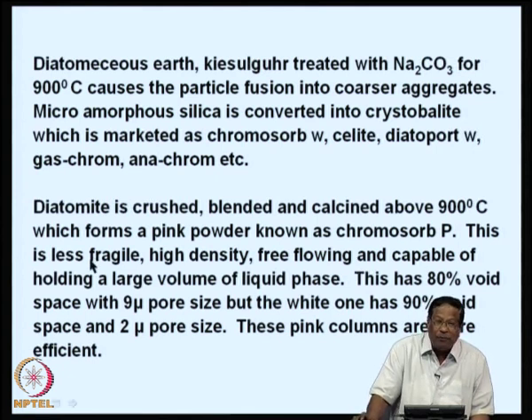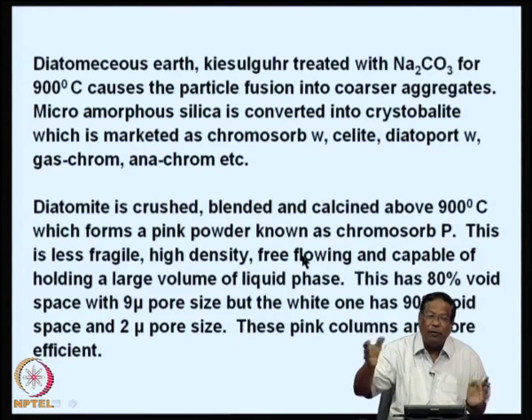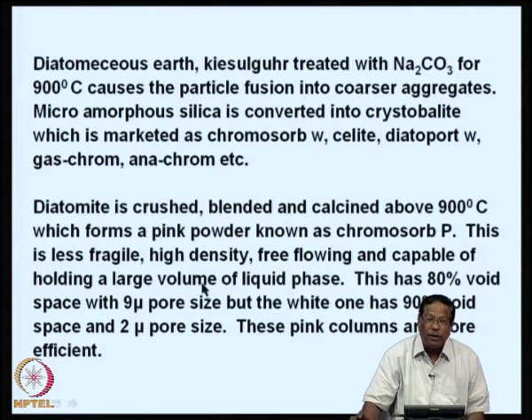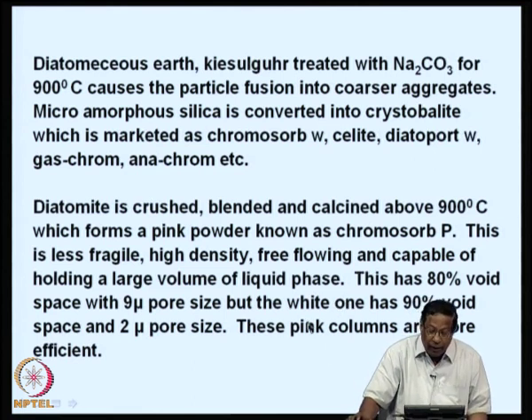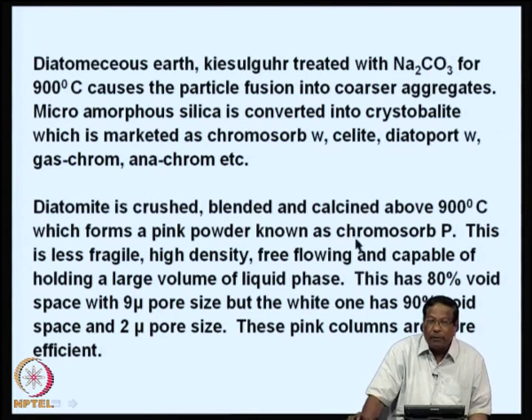So, this is less fragile, and it has got high density, and when you powder it and pour it from the top, it is very free flowing. That means it does not stick to your hands or the container, and it is capable of holding a large volume of liquid phase. This has about 80% void space with about 9 micron pore size, and the one which is marketed as white has about 90% void space and 2 micron pore size. Among the white and pink materials, pink columns are usually more efficient.